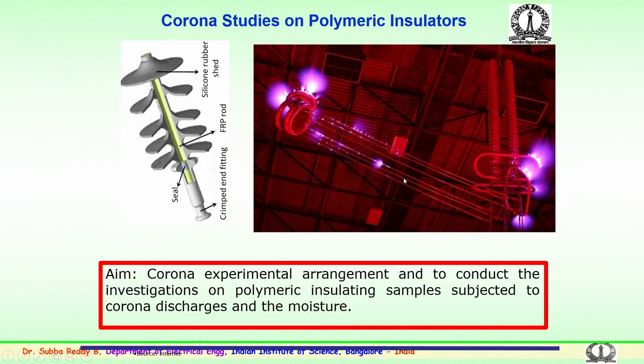Corona, which I was mentioning, could be of two types. One is the corona which comes out from the hardware of the transmission system, the conductors, the corona control rings, and the hardware. You can very clearly see here the corona control ring, and these are the two suspension insulators, twin suspension insulators. The corona generated by the corona control rings continuously interacts with the surface of this insulator, where the continuous bombardment of discharges on the surface is likely to create surface degradation over a period.